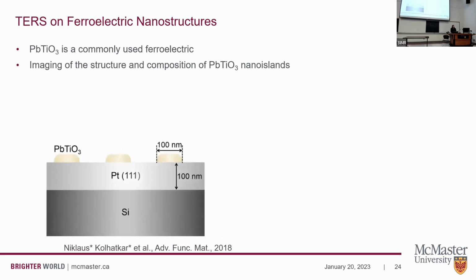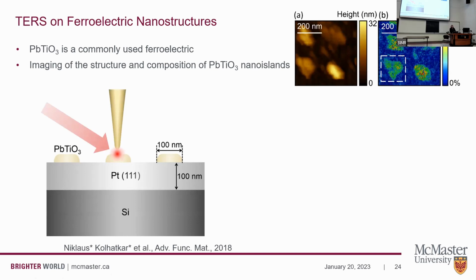And in order to check the potential of this technique, we looked at nanostructures. So here's a schematic of the samples that we looked at. The yellow areas correspond to the lead titanate nano islands, which were deposited onto a platinum substrate. So we took our metallic tip, our gold tip, focused a laser at its apex to generate a near-field amplification and enhance the Raman signal. Here is what we obtained.